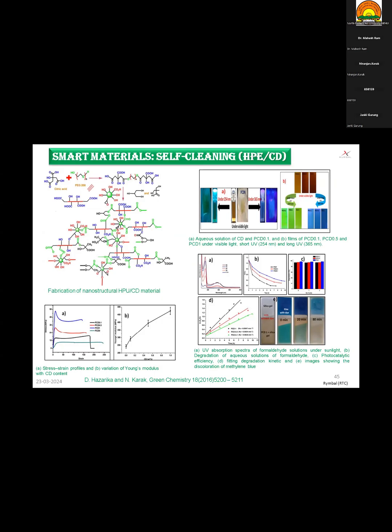So here I have shown a system where, without using any solvent, catalyst, or neutralizing agent, we got a nanocomposite where the nanomaterial acts as a reactant. Carbon dot is used as a reactant, and using this, not only are you able to improve the performance, but you also get a self-cleaning attribute and different-color photoluminescence under different wavelengths of UV light, which can be utilized in signaling systems and auto-cleaning paint.